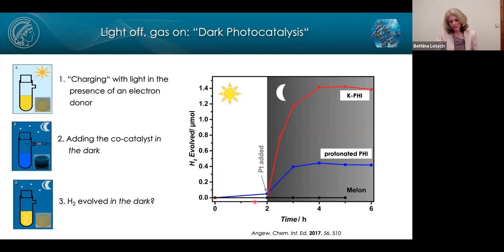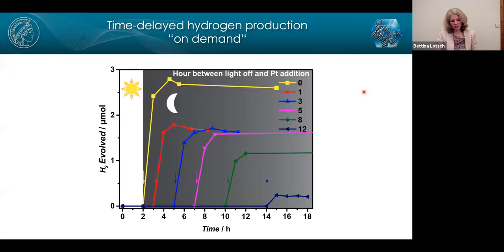What you can see here is a comparison between Melon type carbon nitrides and different PHI type carbon nitrides. So potassium PHI works better than protonated PHI, for example. But what we clearly see is that we can turn off the light and then add the co-catalyst in the dark, and we see hydrogen evolution in the dark. And so this, of course, is only useful if we can decouple the light from the dark phase a bit more. And so this is what we did.